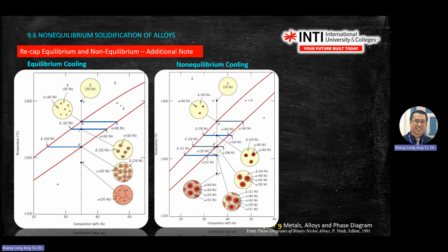But the way you draw it becomes more and more layers. So here you got 3 layers already. This one 2 layers, this one 3 layers. And the percentage always copies the previous one. So the inner layer is 46, the second layer will be 40%, the third layer will be 35%.